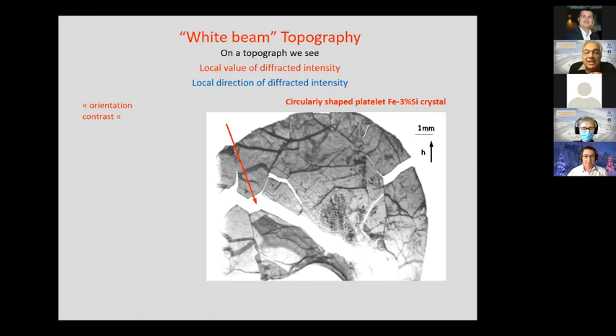and also the local direction of the diffracted intensity. This is the image obtained with white beam topography of a circularly shaped platelet of iron 3% silicon crystal. And you see that the shape is not circular anymore, and you have a lot of holes and also black lines. This is what is called the orientation contrast and corresponds to the fact that you have a lot of subgrain boundaries and subgrains in the crystal.